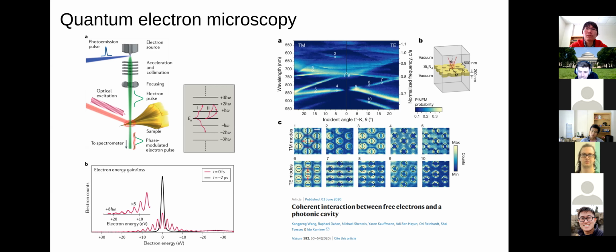So this here is a result from a recent paper by a colleague of ours who has one of these fancy transmission electron microscope setups. They took a photonic crystal slab and sent the electron beam at it with different incident frequencies and also different angles of the photonic crystal slab. By analyzing the electron energy loss spectroscopy data, they were able to reconstruct both the band structure of the photonic crystal slab, as well as make real space images of the photonic crystal modes, which are basically the Bloch modes in the material.